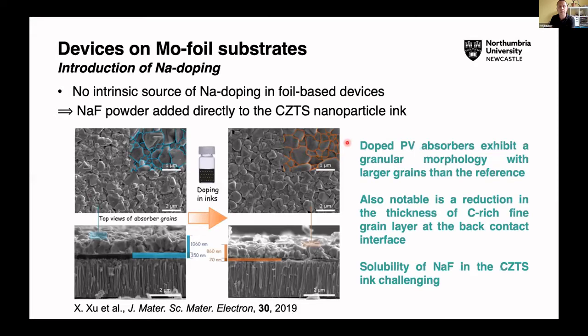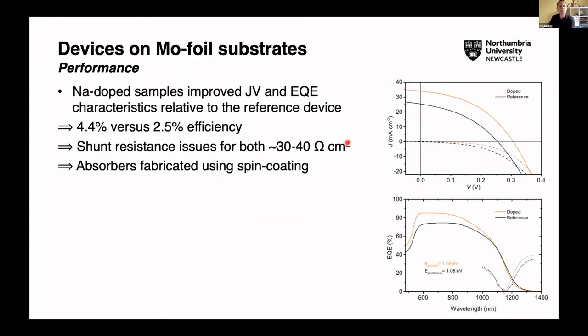These were spin coated, these ones we're looking at, and that's not bad at all compared to, I think, the best nanoparticle ink, or the best flexible molybdenum foil CZTS devices, around 9 or 10%. That was a Nature Comms article a couple of years ago now. So there's our efficiencies, with and without the doping for a spin-coated device, and some of the parameters around the shunt resistance. Well, the shunt resistance needs work.